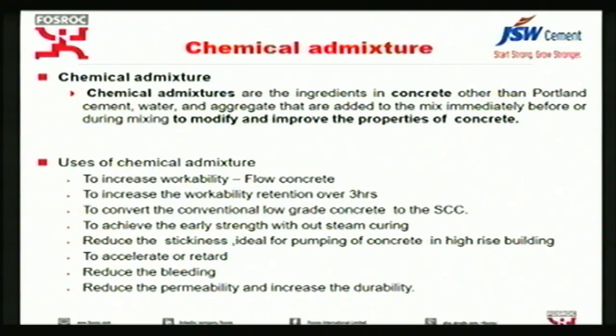And to achieve early strength, of late a lot of precast construction is coming up. People are looking at 8 hours 10 MPa, 8 hours 15 MPa, especially in the precast industry, to make the formwork turnaround very fast. Earlier we used to get early strength using steam curing. With the invention of PC-based admixtures, without any steam curing we are able to achieve 10 to 12 MPa in 8 to 10 hours very easily, which is enough to handle the concrete.